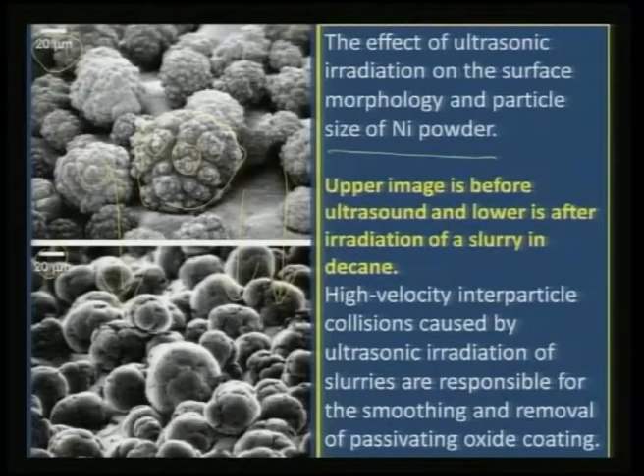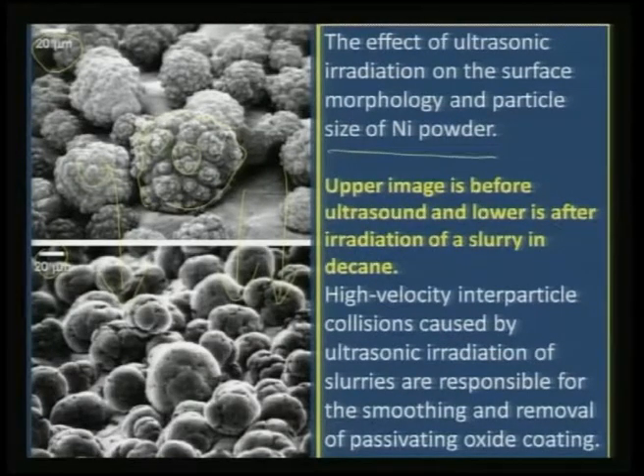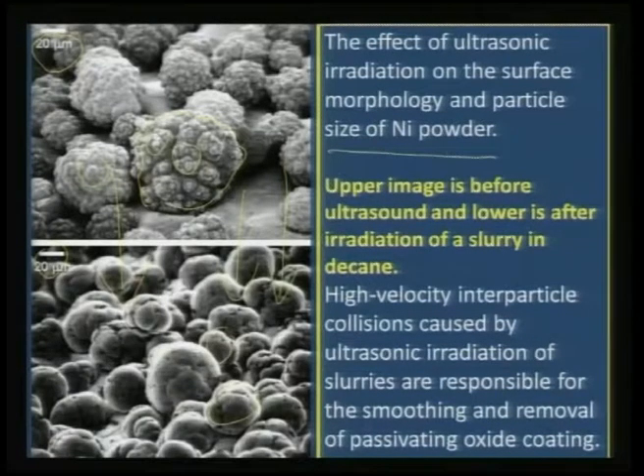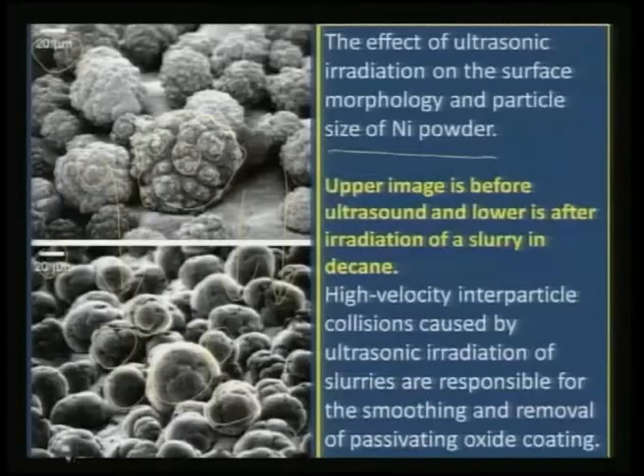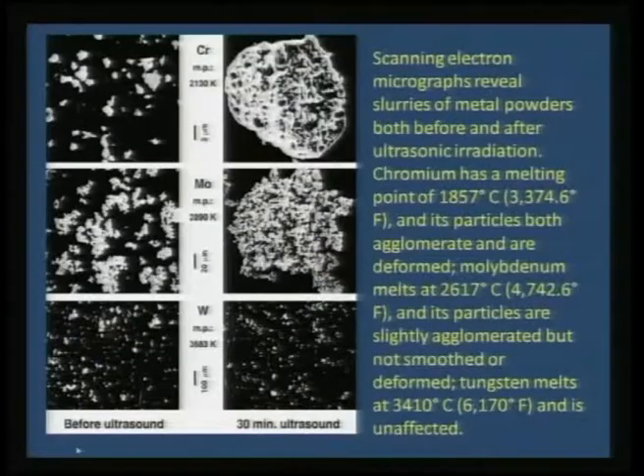What the ultrasound essentially does is remove all passivating layers from the nickel — whether carbonates, hydroxides, or anything similar — and can also break particle size into smaller, nearly uniform ranges. Therefore, one can say uniform surface-polished nickel particles become highly reactive, comparable to Raney nickel. You can remove passivation and bring forth a variety of interesting features with ultrasound.